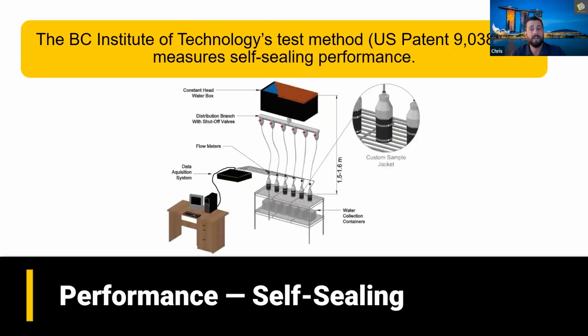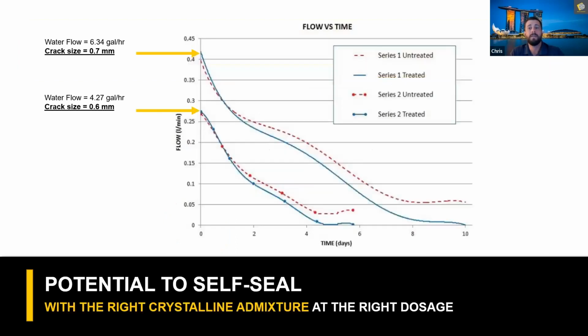So Kryton, we are an expert in this field. Kryton and the BCIT actually invented and patented a very accurate test method used to measure self-sealing performance. This test, along with our method of inducing cracks to get consistent crack sizes, is not only used in our lab, but also in others, including the British Columbia Institute of Technology. So with this test, hydrostatic pressure is applied to the cracked concrete and measures the flow rate through the crack over time. And this is what they learned. The graph shows how the self-sealing of concrete is greatly enhanced through the addition of a particular crystalline admixture. The dotted red lines show the control concrete samples with 2 different crack sizes and the resulting water flow, while the blue lines are for the crystalline treated samples.